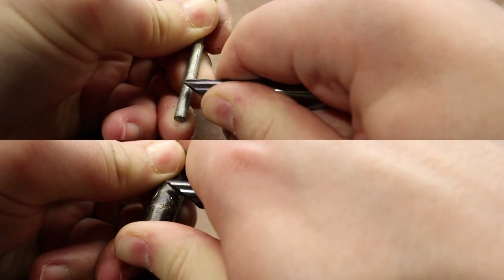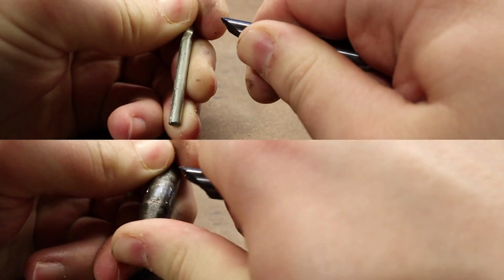Tungsten, usually in the form of cemented carbide, is seldom used in portable weapons for 2 reasons. The first is that tungsten is expensive both to extract and manufacture. For a penetrator core, we're looking at no less than $50 per kilo. But there is another strictly technical reason, which is even more important than the first one, and which is the subject of today's riddle, so guess it in the comments.